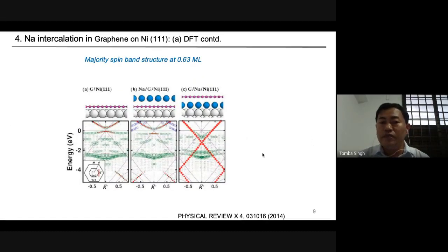This is the main important result from the DFT calculation. Here it shows the majority spin band structure at the reference point, 0.63 monolayer coverage. As we have shown in the system model, the graphene on nickel, with sodium above the graphene and sodium below the graphene. What is the change in the band structure?